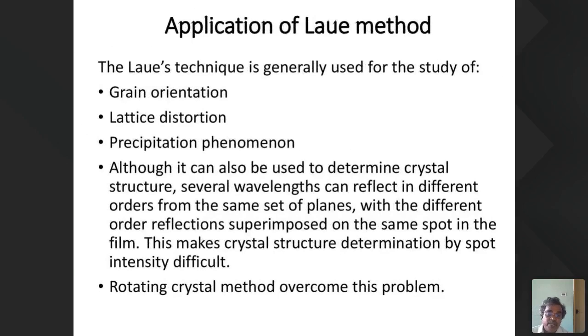The application of the Laue method is that you can study the grain orientation, lattice distortion, precipitation phenomena, etc. Although it can also be used to determine the crystal structure, several wavelengths can reflect in different orders from the same set of planes, with different orders of reflection superimposed on the same spot in the film, which makes crystal structure determination difficult. So this can be avoided by the rotating crystal method.